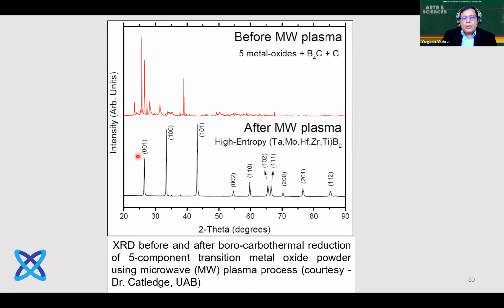And after you have done your plasma treatment, you get a very simple crystalline structure, which is hexagonal and is basically equimolar tantalum, molybdenum, hafnium, zirconium, titanium boride. So this is a one-step process for making these powders without use of high pressure. And this is just the beginning of, I think, work on the high entropy material by low temperature plasma.